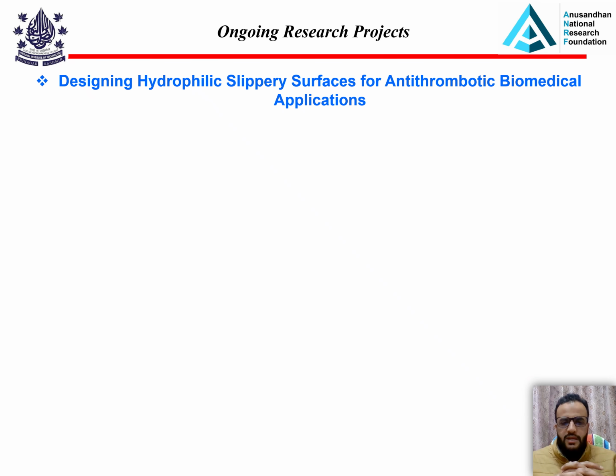Our next ongoing project is designing hydrophilic slippery surfaces for anti-thrombotic biomedical application. As I mentioned in my slippery surface project, the hydrophobic slippery surfaces means when the contact angle is very high, above 90 degrees, we call that hydrophobic, and when the droplet slips away from the surface, it is called a slippery surface, and those surfaces are hydrophobic slippery in nature. So in this project, we aim to design a hydrophilic slippery surface for anti-thrombotic biomedical application. So basically, this is a counter-intuitive surface. Generally, hydrophilic surfaces are water-loving surfaces, so they are not able to release the water present on the surface, so the water droplet is hard to slide on the surface.